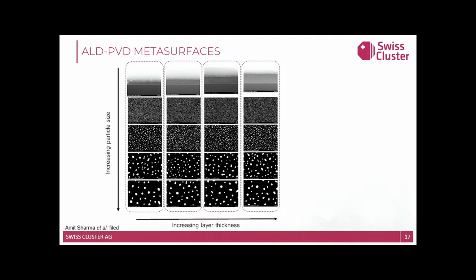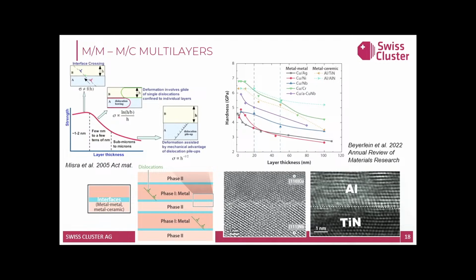So with this type of approach, we can tailor the spatial distribution of the nanoparticles, the nanoparticle size, by tailoring the thickness of the interlayer of this aluminum oxide, but also by increasing or decreasing the particle size in all of the different directions. So we observed that most of the properties that we can obtain combining this multi-layer system is increasing the temperature, the thermal behavior, and the mechanical behavior, right?